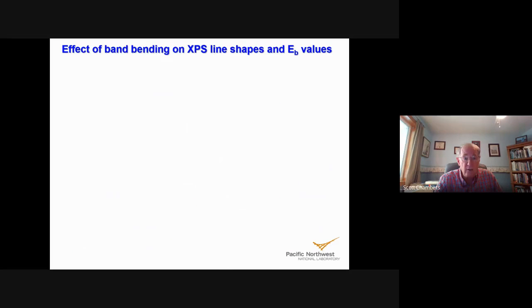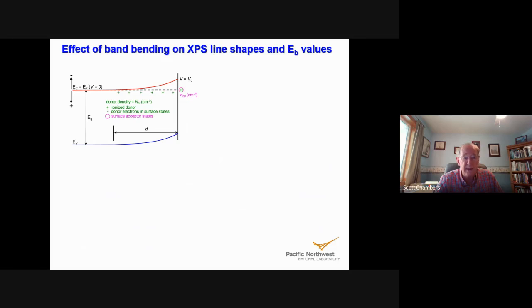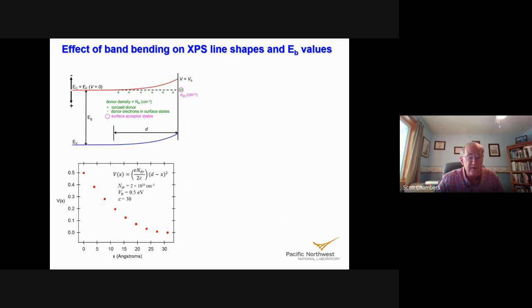To show you how that works, let's just go back to the band bending of a single semiconductor as an example. Well, we can set up and solve Poisson's equation for a freestanding semiconductor like that. And so if we do that, I've picked, somewhat arbitrarily, a bulk doping density of 2 × 10²¹ per cubic centimeter, a band bending of half a volt, and a dielectric constant of 30. And I can calculate what the potential is going to be as a function of distance from the surface, and that's shown here in red.